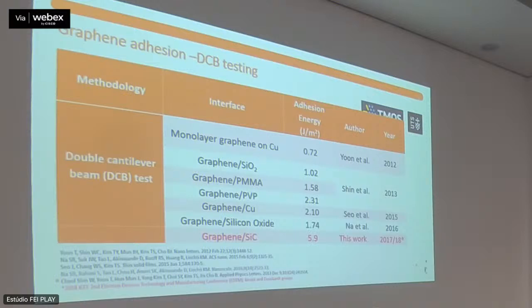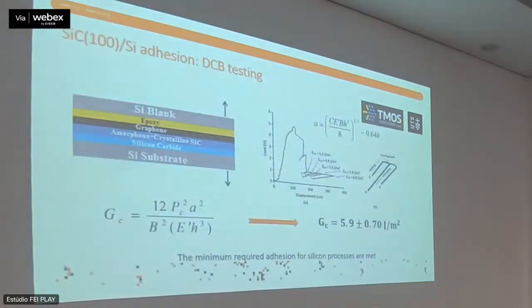Now, this is interesting because clearly this is not just van der Waals forces, right? This is just an example. We used the DCB adhesion testing with our standard collaborators, and that's the number we came up with. So it's not just van der Waals forces. Remember that I mentioned that we had about 100 nanometer grain size. Basically, the grain size is the effective size, and at that effective size you can potentially have bonding to the substrate. So basically it's all about the sweet spot.